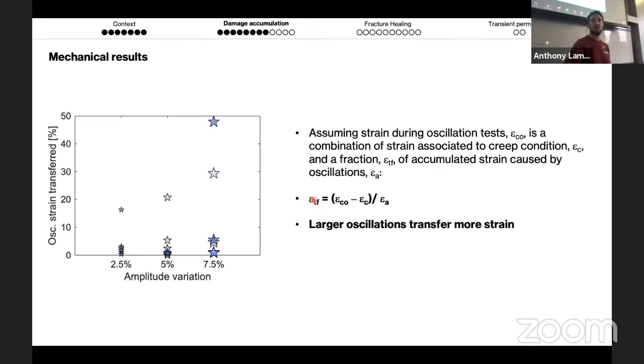Now, if I assume that the strain accumulated during the oscillation events is a combination of the strain accumulated during the creep phase and the strain accumulated by the individual oscillations, what we can find is the fraction of this accumulated strain that is transferred from elastic to inelastic. And again, what we'll see is that larger oscillations will transfer more strain to the sample, or will basically create more inelastic deformation in the samples. Okay, bigger oscillation, more strain is being transferred to the sample.